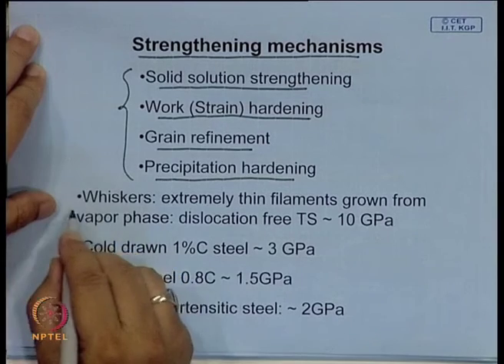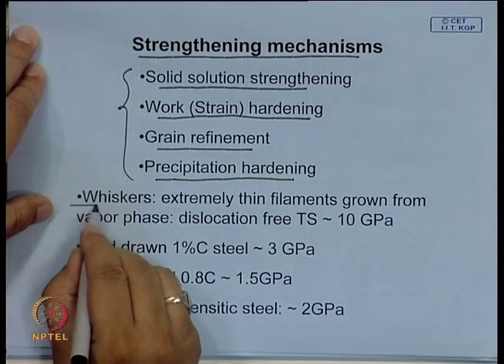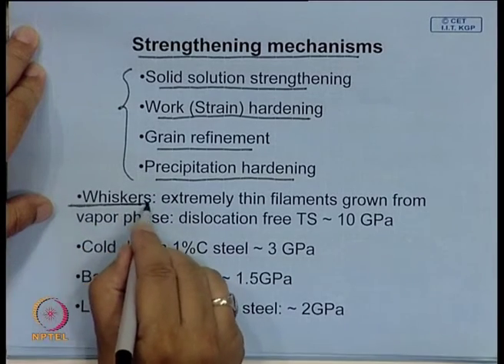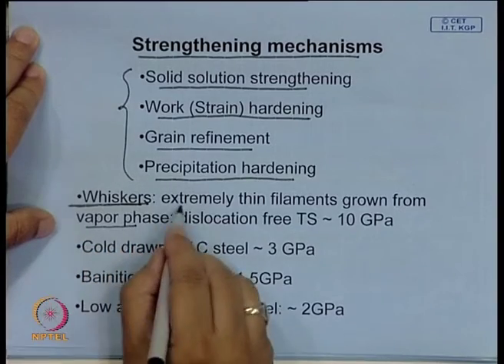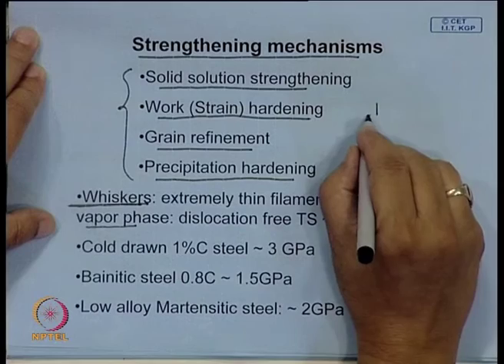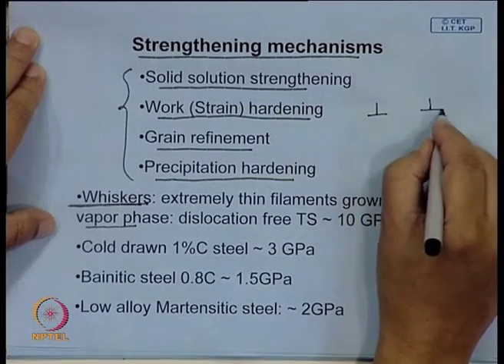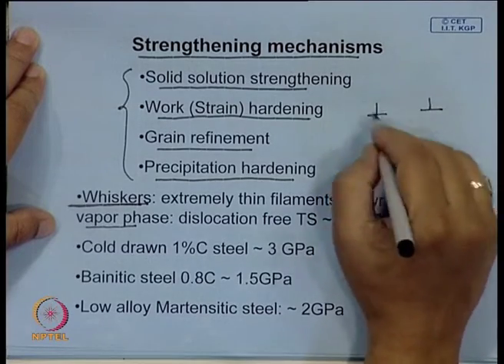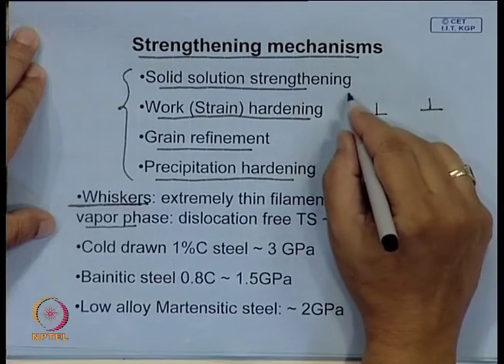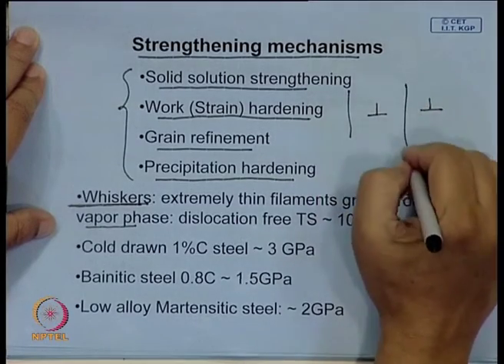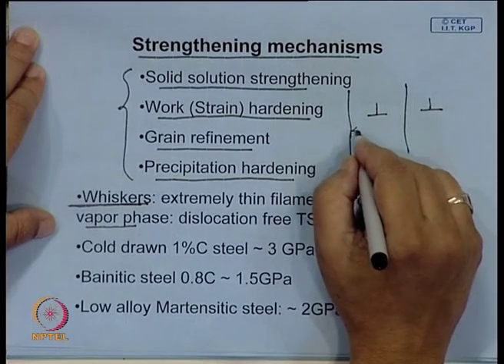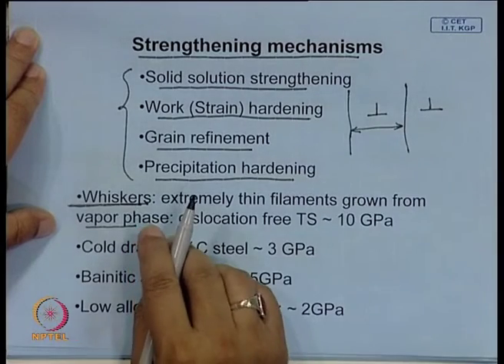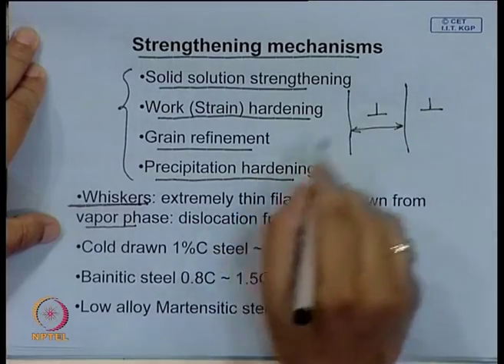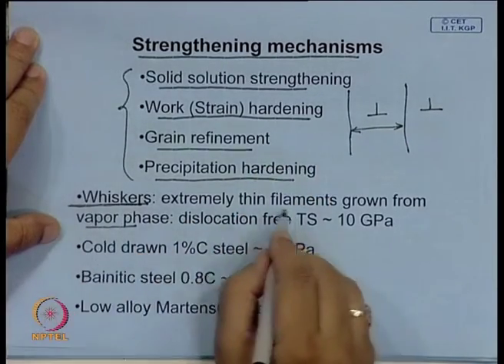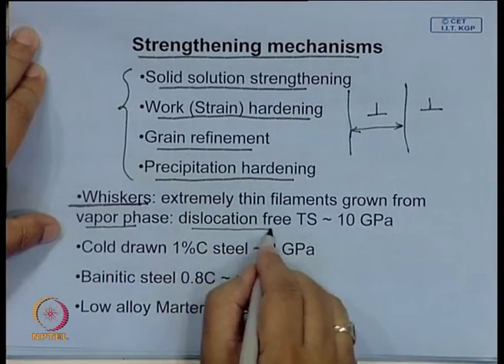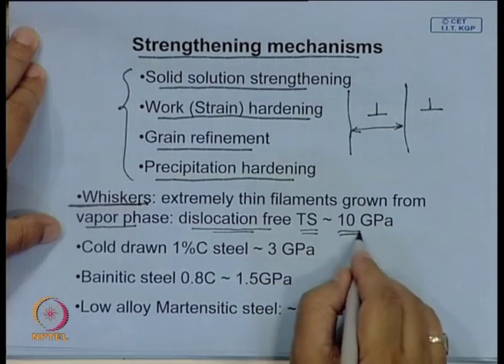Just to give an idea, what is the strength of steel? Iron can be made in the form of whiskers. These are very fine filaments which are grown from vapor phase, and these are so fine, that normally we have seen the dislocations have a stress field, so two dislocations cannot stay very close by. If the dimension is very small, it is impossible to accommodate a dislocation, and it is quite likely that this material will be defect free. These whiskers are very thin filamentary crystals, virtually dislocation free, and their tensile strength is of the order of 10 GPa.